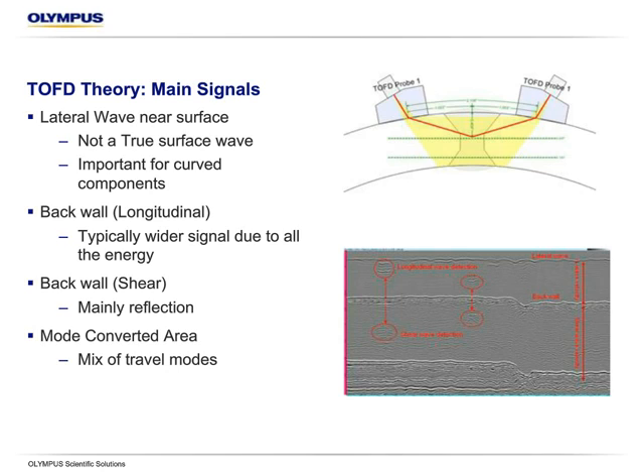The other one is the backwall signal, which is also typically majority longitudinal wave. It's typically a very wide signal, which can cause some resolution issues at the back, another area that we call a near blind or an area of concern. Not as much as the lateral wave, because we can actually make some focusing and other adjustments to make this very small indeed, but there will always be some very small zone at a minimum that is an area of concern that we want to be cognizant of at the back wall.